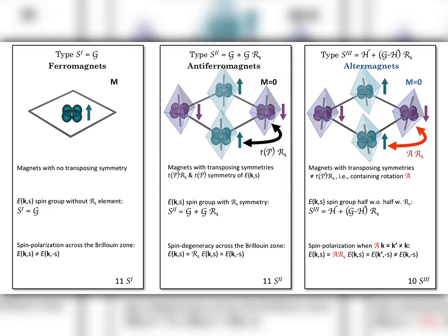Now, when I look at my band structure, because all my symmetries are such that they do not contain this spin rotation operation, for any k vector and spin, when I look at the eigenenergy of the reverse spin, it's in principle different because there is no symmetry operation that would connect eigenstates with opposite spins. So my band structure is in principle spin polarized.